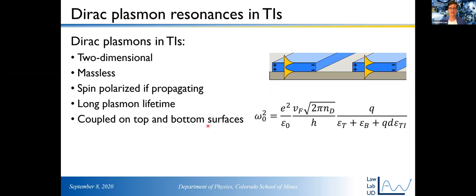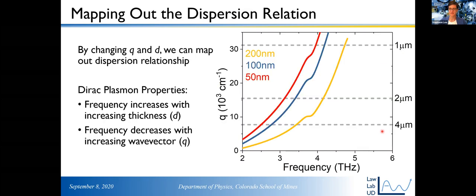And it turns out that some theorists who are much smarter than me calculated what the dispersion should look like. And this is what the dispersion should look like. So this is telling us what the frequency of this coupled Dirac plasmon polariton should look like as a function of wave vector and as a function of film thickness here, which is going to become important.